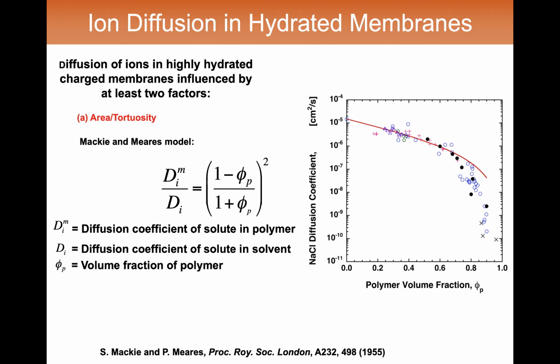Now, this picture is quite different from the one that we developed for ion diffusion or penetrant diffusion in polymers, for example, for gas separation applications, where the penetrants were relegated to staying in a free volume cage that was defined by the neighboring polymer segments, and the only way they got to move is when there was sufficient molecular motion in the polymer segmental backbone to open a gap large enough for the gas or small molecules to take a diffusion step.